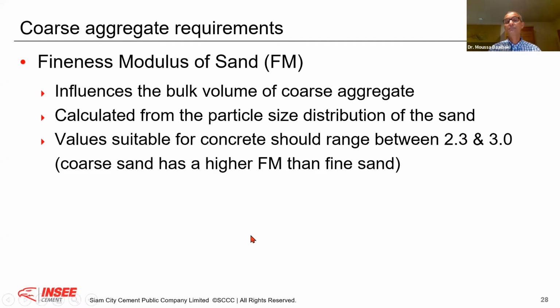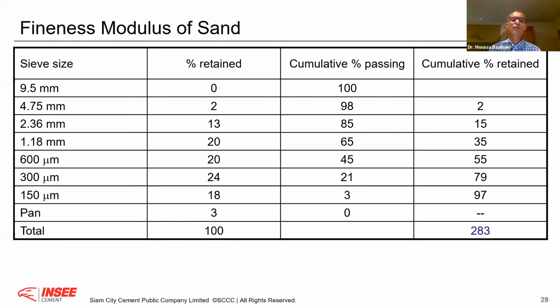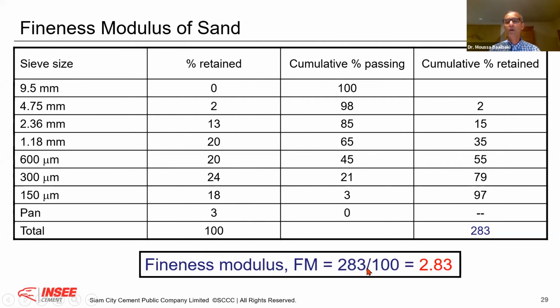And you can experience that if you walk around, you go to a job site, and you will see it sometimes. Therefore, fineness modulus is very simple. You have your sieve opening, percentage retained, you get the cumulative passing the sieve, and you get the cumulative retained. If you add the numbers between the 4.75 millimeter and the 150 micron and divide by 100, this is your fineness modulus, 2.83. Very simple. But this is a very important characteristic of the sand, because you will see in the next slide.